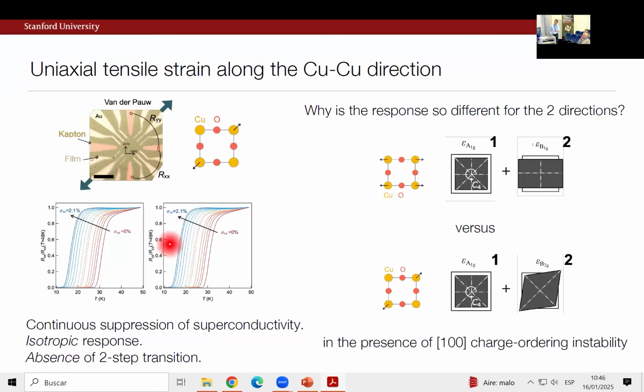Just to summarize, what we see is an isotropic response. We have a suppression of superconductivity, whether we're in the stretching or compressive direction, and we don't see any of these two-step features. So our working hypothesis right now is that the reason for the response being so different is in terms of the contributions of the strains being generated,